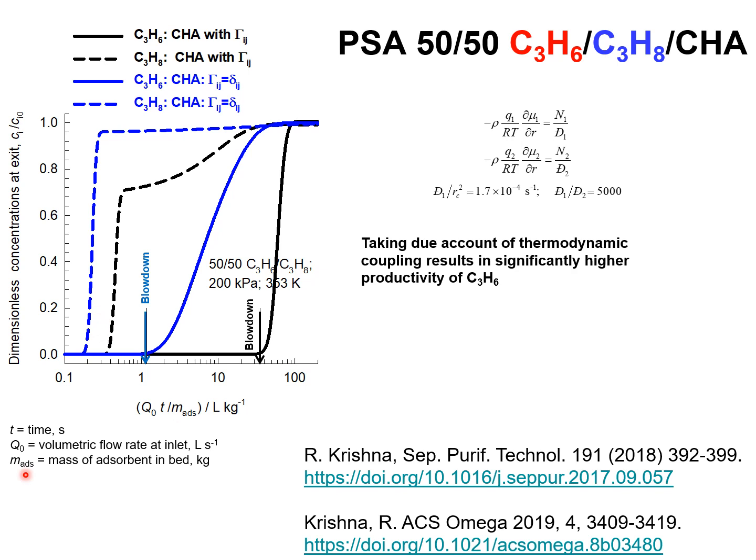There are important differences between the black simulations and the blue simulations, and these differences are largely with respect to the times at which propene breaks through. If thermodynamic coupling effects are duly accounted for, the propene breaks through later.